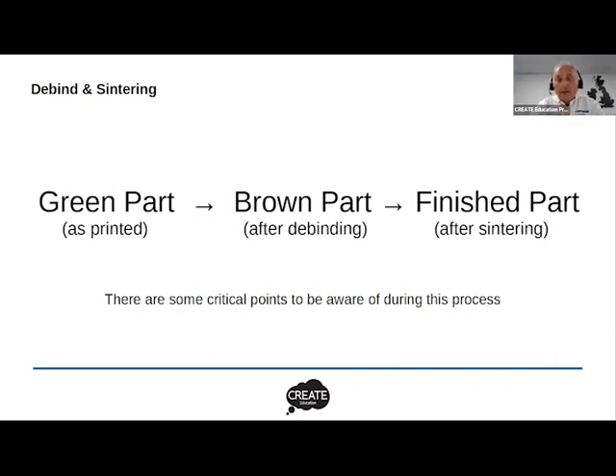And at that point, all of the backbone polymer is gone. And all that effectively is left then is stainless steel powder. So the part needs to be able to hold its own weight at that stage to successfully go through the sintering process. So that's a brief overview of green part to brown part to finished part.